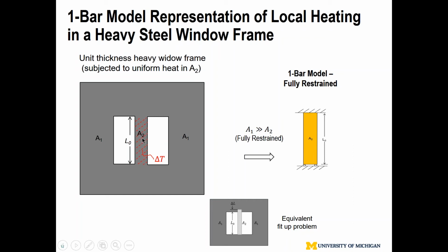That's one aspect. Another aspect is high strength steel. Obviously you have to use a thinner gauge when you introduce high strength steel. Meanwhile, the residual stress is pretty much proportional to the yield strength of the material. Using shipbuilding terminology, this is essentially A36 steel at 36 KSI versus 80 KSI. The residual stress produced, causing welding distortion, is about twice as much. In the meantime, you may want to reduce the thickness by, let's say, 50%. Now, combining the factor of 4 with double the driving force, internal stress, we have a big problem. So without getting into detail, thin section and high strength are much more prone to distortion, because you are talking about not just a factor of 2, not just a factor of 4, and that means there's a quantum leap.